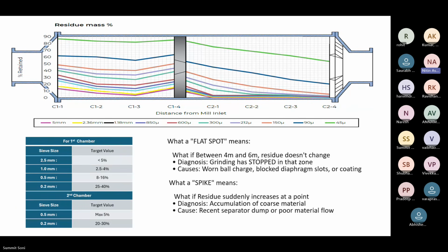Whatever the sieve size is, you're talking about the first chamber at 2.5 mm, target value less than 5%. This is for the first chamber, just at the intermediate diaphragm. So what we do is we start removing the balls next to the intermediate diaphragm, and we remove a good 1 foot, almost 12 to 14 inches. Then we pick up the sample next to the wall of the diaphragm.